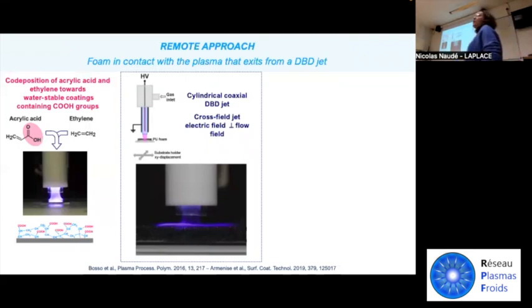We also explored another possible approach, that is the remote approach, in which you don't need to place the sample within the electrodes, but the sample is outside the plasma source, in contact with the plasma that exits from a DBD plasma jet. As you can see here, we tried to evaluate the possibility of depositing a water-stable coating containing carboxylic groups on a foam. In a first study, we investigated the deposition on a classical flat silicon substrate. And we tried to transfer this process to the foam.